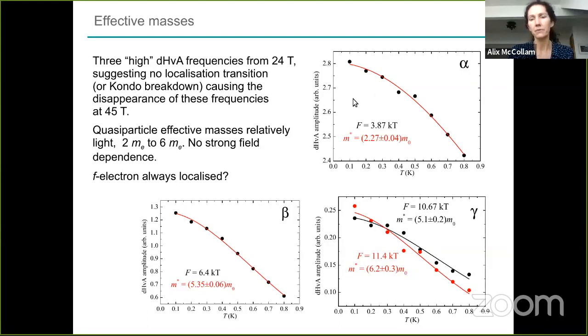And then we can fit these to the Lifshitz-Kosevich expression. I gave the damping factor at the beginning of the talk. This is an x over sinh x function that allows us to extract the effective mass of the quasiparticles. So they're small: 2 electron masses, 6 electron masses, 5 electron masses, so not really very large. At low field, the masses associated with the lower frequencies are also on the order of 2 electron masses. So they're renormalized, but they're not very strongly renormalized.